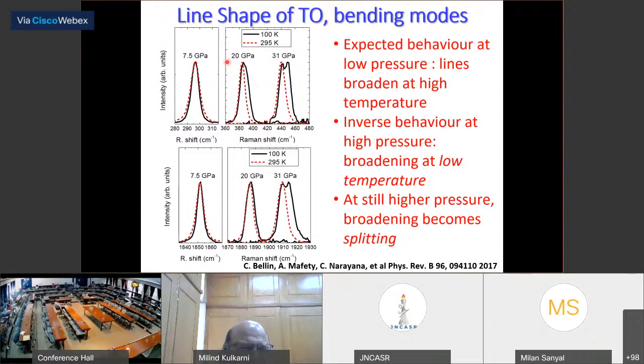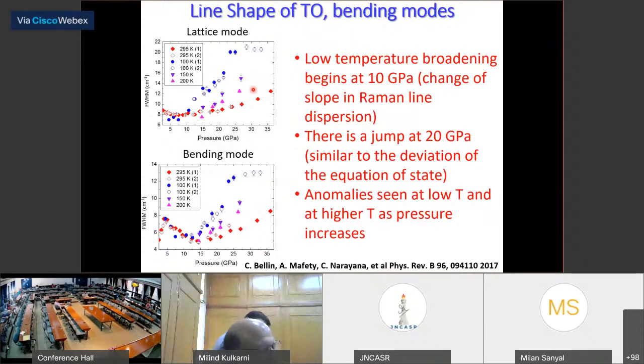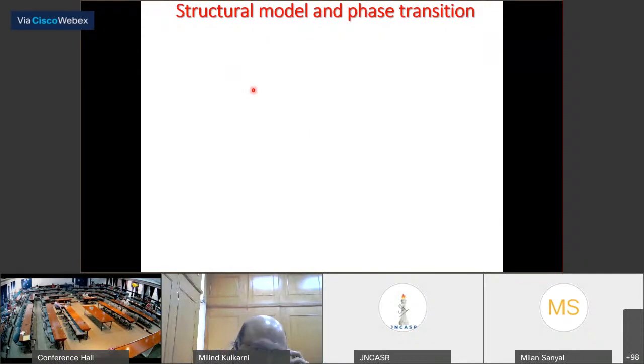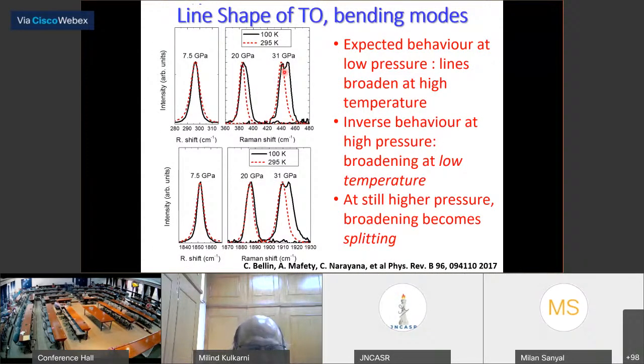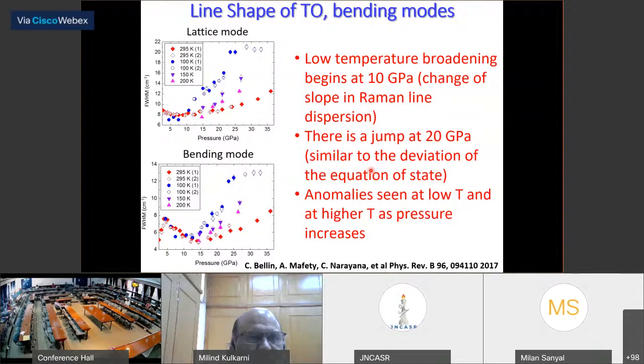But as soon as you increase the pressure, for a low temperature, you start seeing a broadening. This is not easy to understand because it is an inverse effect. At higher pressures, we are seeing that the low temperature is going to broaden, and it is also splitting. This is only possible if there is some sort of disorder to order transition happening in the system. So you have a cubic system which is ordered at lower temperature and higher pressures, but it is actually disordered. You can see the FWHM jumps at 20 gigapascals.